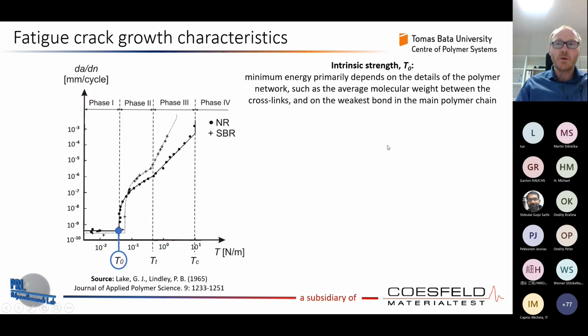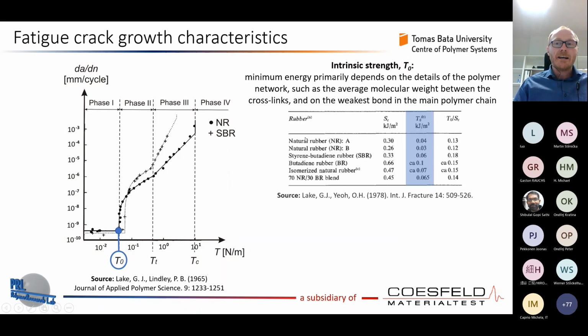We have T0, which is an intrinsic strength, as Chris introduced, which is the minimum energy and primarily depends on the details of the polymer network, such as the average molecular weight between the cross links and on the weakest bond in the main polymer chain.